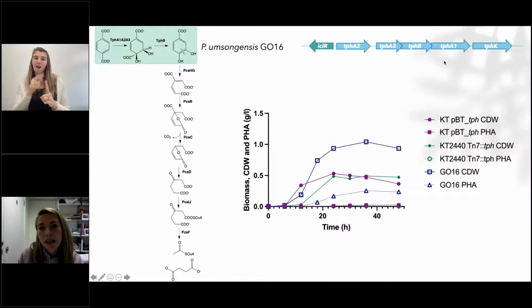And we have then placed this operon into aforementioned KT2440. And what happened was KT2440, that didn't have the capacity to grow with terephthalic acid before, now can grow with terephthalic acid. But what we have noticed is that if you look at the biomass of GO16 here and compare it to the biomass of KT2440 equipped with the same genetic complement, KT2440 can achieve about half of the biomass that GO16 can, and very low amounts of PHA.